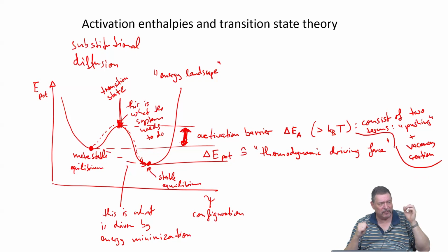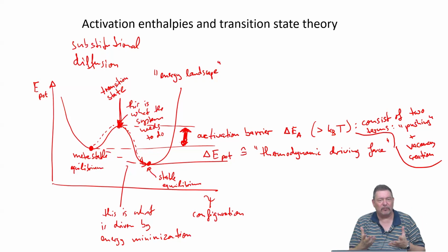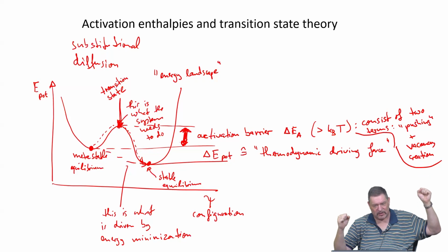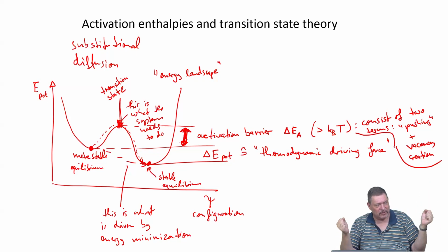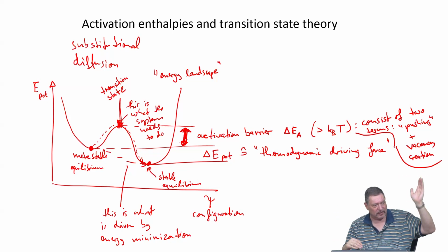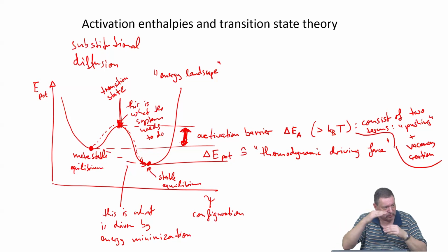So this is very important when you see in the papers these potential energy landscapes. Often they are just a crude picture of what people think might be happening, but they often don't realize that whenever you have a directionality in the process, like applying any type of field, you basically have to consider that the energy landscape is changed, and that with the gradient you basically tilt and shift the landscape so that any processes go downhill more easily. So you change the activation barrier heights.